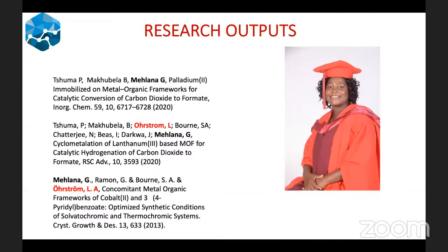In terms of the solvent that we used, ethanol, most literature reports show that in the absence of solvents such as ethanol, which are very important in facilitating the proton transfer, at times you don't get any product. But of course, I would suggest that control experiments would be very useful to ascertain that what we have proposed is not contributing to the formation of formate from our catalytic system.